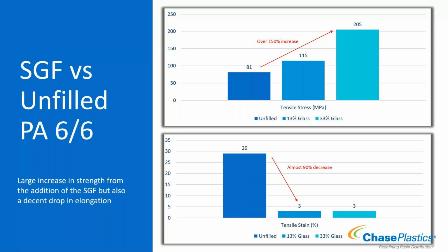And if that's what you need out of the part, that's what you get. The downside is glass doesn't like to elongate - it doesn't pull apart and stretch. So you see a big drop: unfilled at 29% elongation drops down to 3%, and it's 3% for both 13 and 33 glass. Glass doesn't want to move regardless of the amount in there. You lose your elongation when you add glass to something.